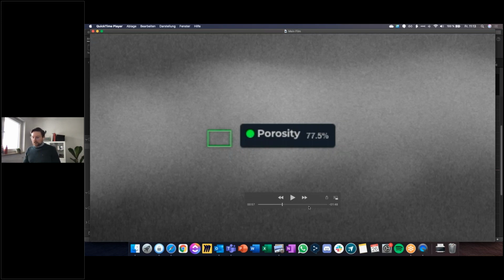And then what we can see here also is that we have an indication of the probability, although this percentage is not an absolute value, that the algorithm is 77.5% certain that it is a porosity. It needs to be understood as relative. So in this area, which is marked there, 77.5% of those pixels, so each and every pixel is classified, are classified as porous, and that is where this result comes from.